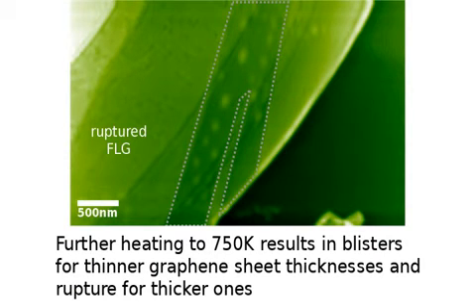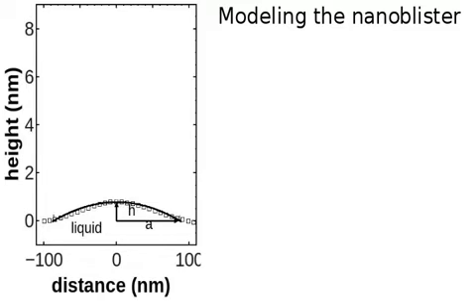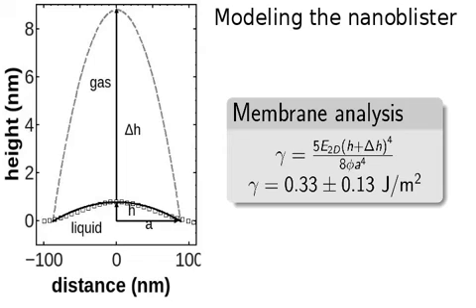Upon cooling, the water vapor condenses into liquid-filled nanoblisters, from which we can estimate the adhesion energy for graphene and calcium fluoride 111 by measuring its dimensions.